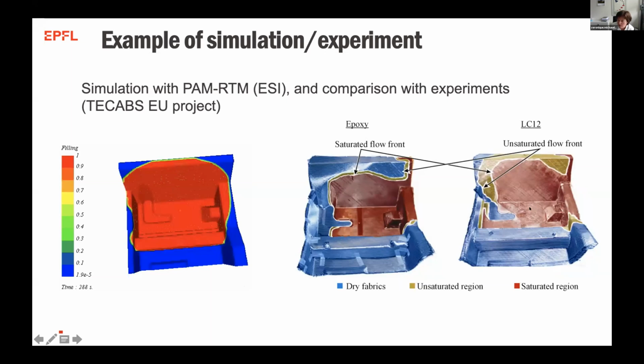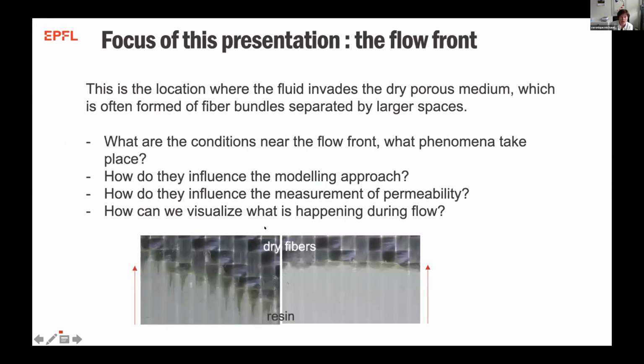What's interesting also is to see what's happening at the flow front. When we stopped the experiment in these two cases, we see that there is some kind of unsaturated zone, which we put in yellow here, which is much bigger in one case for LC12, which was a thermoplastic precursor, than it was for epoxy. So what's happening here is really what we're interested in today. If you look at these pictures down there, we have the same fabric, same resin, but two cases where in this case the flow front looks very uniform, and here the flow front doesn't look uniform at all. And this has an influence on the quality of the material afterwards as well.